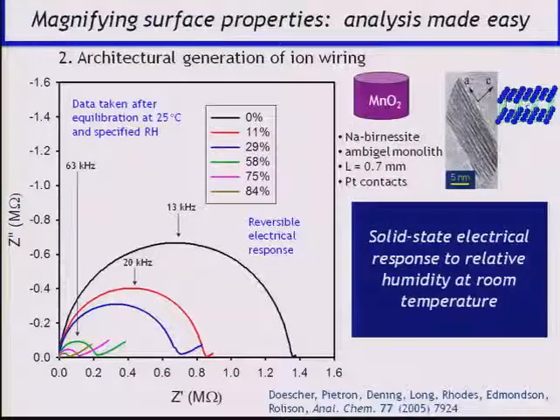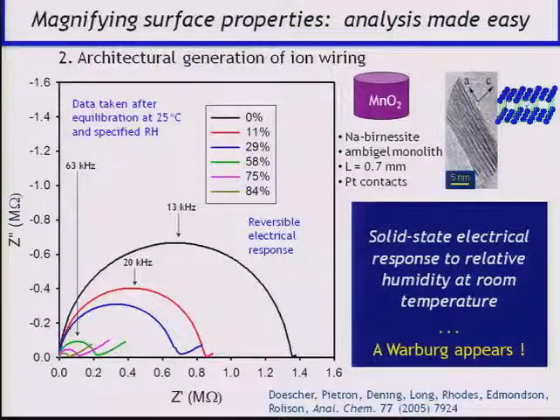bottom electrode contacts. We're equilibrating with different concentrations of water or relative humidity at ambient temperature, and when we're as dry as we can get it, it's a beautiful arc. And the minute you start introducing relative humidity, 11, 29, 58, 75, 84%, it gets much less resistive. You lower the impedance. And that, of course, is the signature that you're moving protons. But the other thing that shows up here is a linear element, the Warburg.